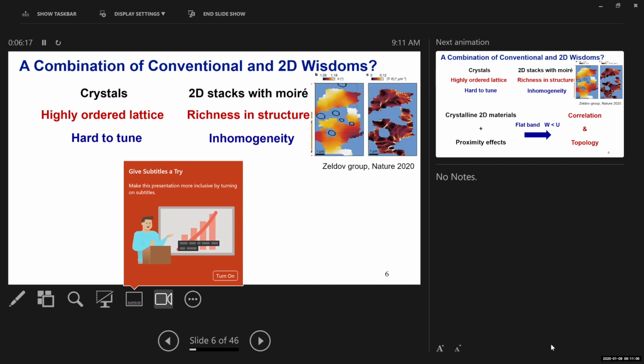For example, this is a work to use a scanning nanosquid to image twisted bilayer graphene. And because you may have heard, there's a so-called magic angle between graphene and graphene that gives you superconductivity. But the thing is, that magic angle is very precise.